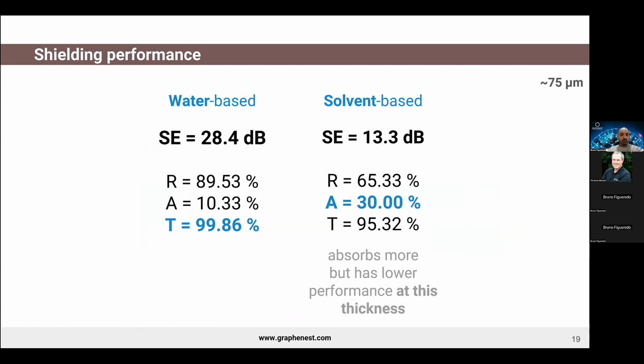If we take into consideration a thickness of 75 micrometers, as we can see, the water-based provides 28 decibels of attenuation, shielding, while the solvent-based only 13 decibels. However, when we look at the shielding mechanisms behind these numbers, we can see that the solvent-based has a bigger contribution of absorption, which again might be important for certain applications. So at the end, solvent-based ExiShield absorbs more, but has lower performance at this thickness. If you want to make it work better, you need to increase the thickness.